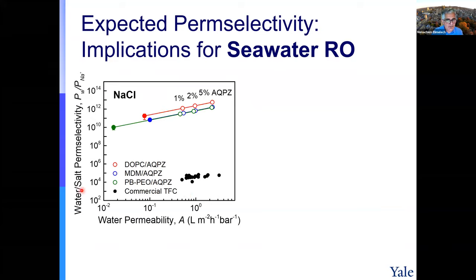This is the water-salt permselectivity. The higher the value, the more the rejection. You want to get high rejection. And this is the water permeability. This is the data for commercial membranes, which we took from different TFC modules, from the companies and the literature. And this is what you expect. If you have about 5% aquaporin Z, which was the optimal to get the right permeability, you see that we can get water-salt selectivity many, many orders of magnitude more than the current membranes. For sodium chloride you will get much higher water-salt selectivity, and this corresponds to 99.999% rejection.